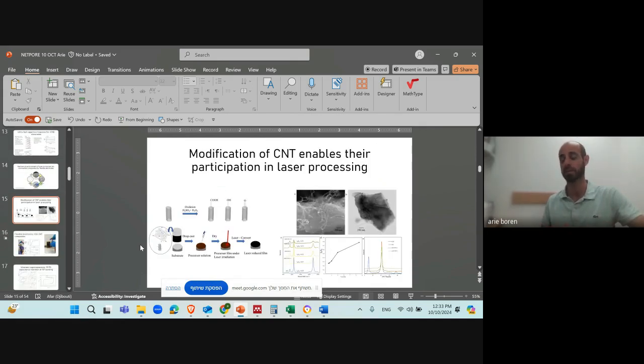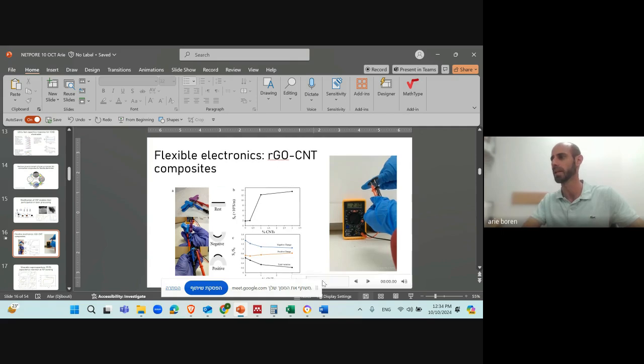So what we did, we mixed the graphene with carbon nanotubes. Okay, so we simply mixed graphene oxide with carbon nanotubes, and they underwent a very special chemical modification, where we just added on the carbon nanotubes these functional groups that we talked about that will react with the laser, otherwise it won't work. And you see in the microscope images that we have the graphene sheets, and in between the sheets we have the nanotubes. Okay, and the idea is that the nanotubes interconnect the particles of the graphene. Okay, so in case of stretching or bending, where the particles are being separated, the nanotubes will retain the conductivity. And this is indeed what is happening.